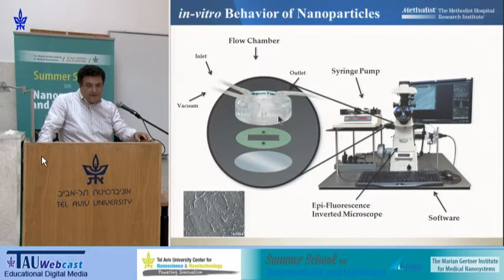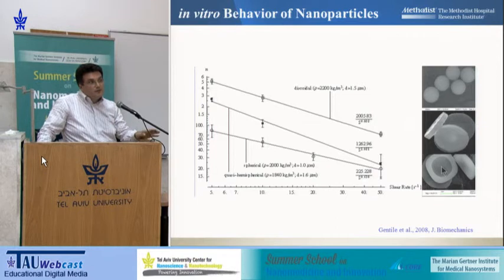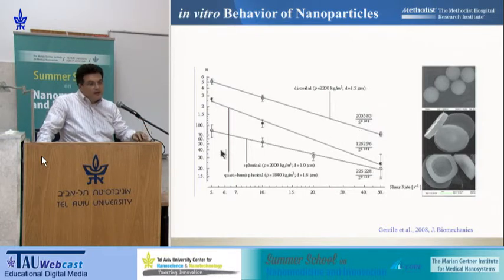And here in this room, it's Annalisa Palange, who is sitting here, that has been working extensively on these systems and characterizing their in vitro properties. So we showed using these systems that if you look at the adhesion of discoidal particles that are coin-shaped, so thin discoidal particles versus spherical and versus quasi-hemispherical particles, because the first version of the silicon mesoporous particles was not discoidal, was quasi-hemispherical, you actually have the discoidal particle adhering and sticking to the bottom of this chamber in a larger number as compared to the quasi-hemispherical and compared to the spherical, for the reason that I just said before.